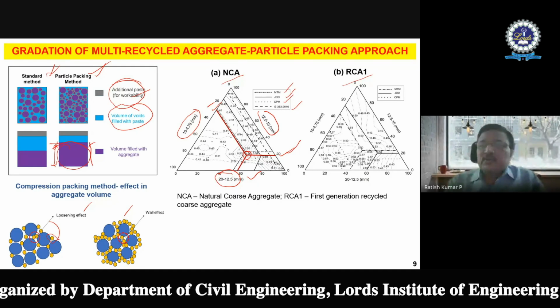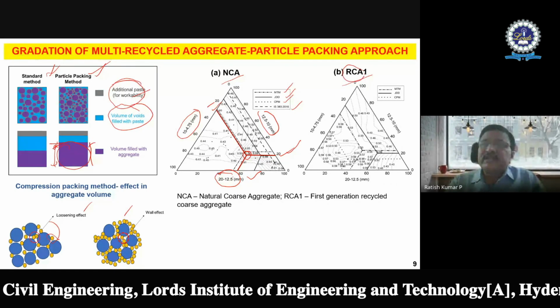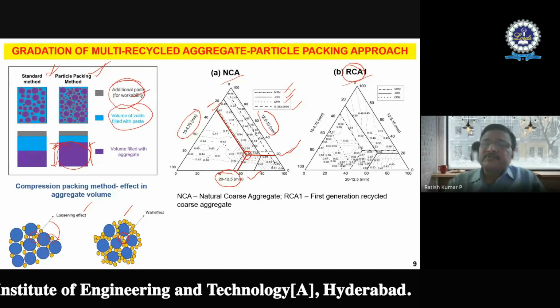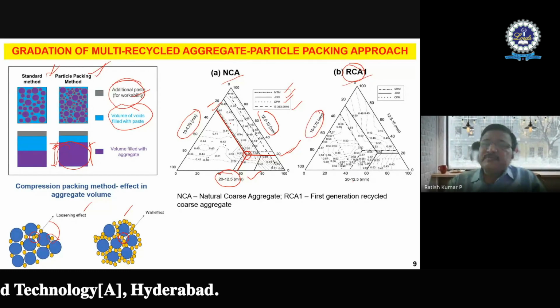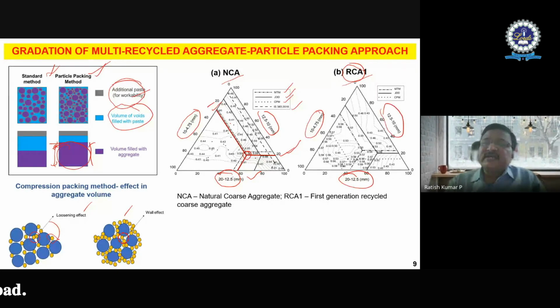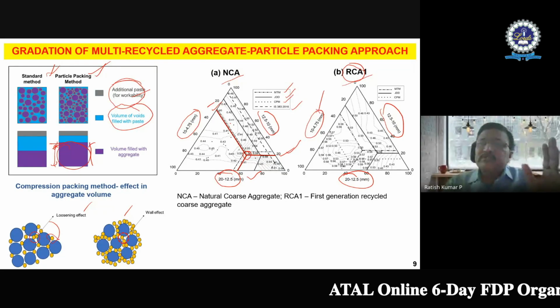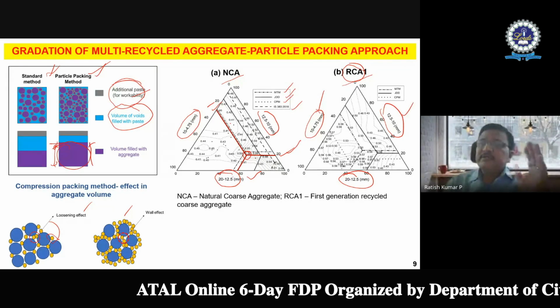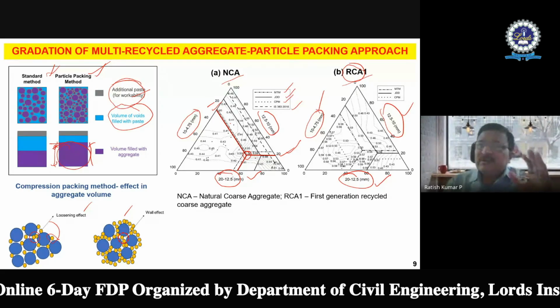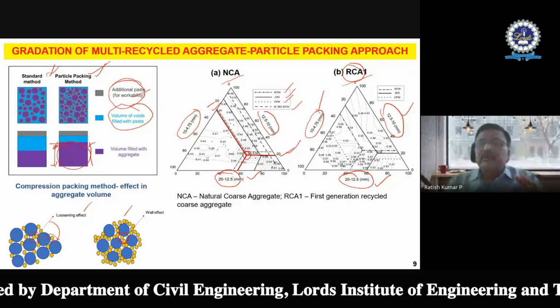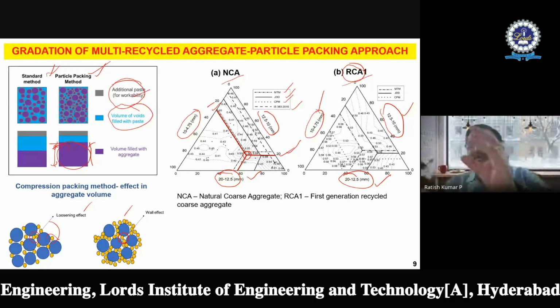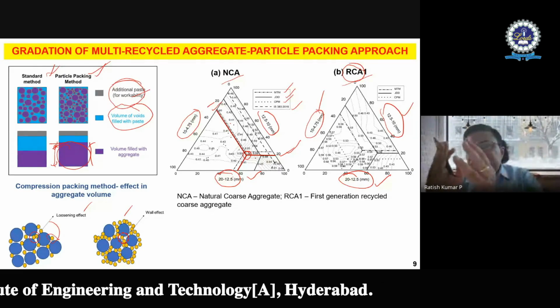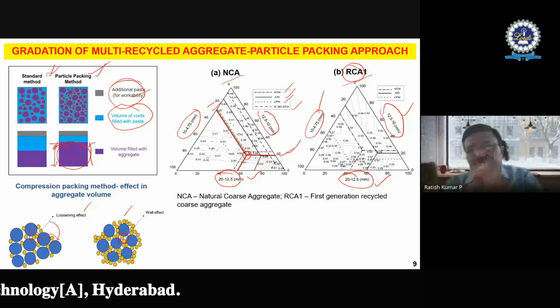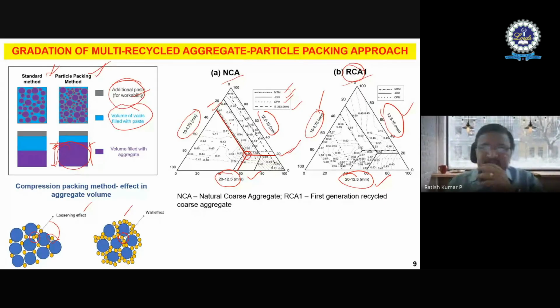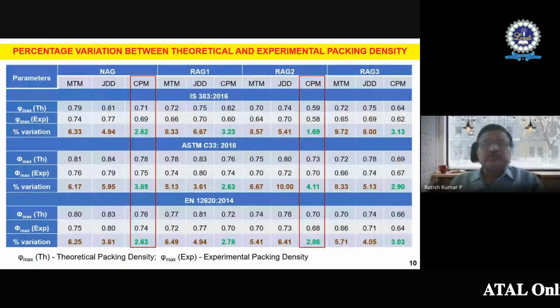So the same thing, as you can notice, I'm trying to show in the case of recycled aggregate also. The same approach is adopted, and then you do the gradation based upon the different sizes of the aggregates, and then you try to arrive at what percentage is passing through 10 and 4.75, passing 12.5, and passing 20 to 12.5 can be taken as an example. I'm trying to tell you that you can take each of these different percentages to get a packing in such a way that there is very little room for voids. That is what is called the concept of the particle packing approach.